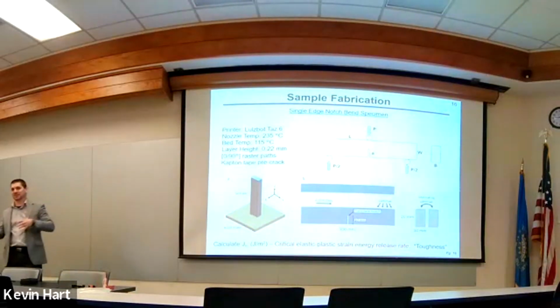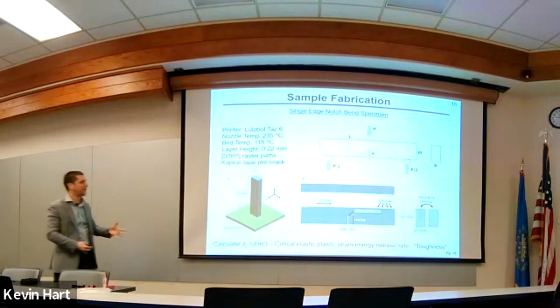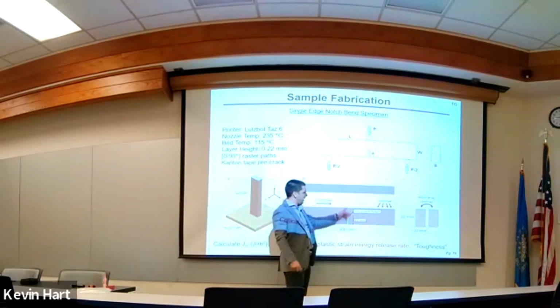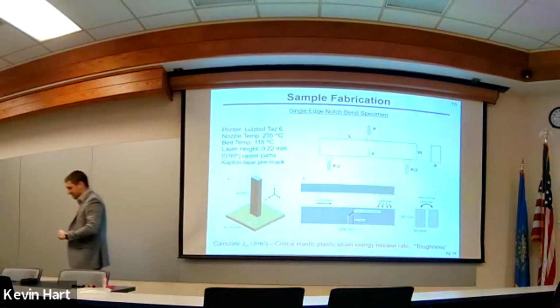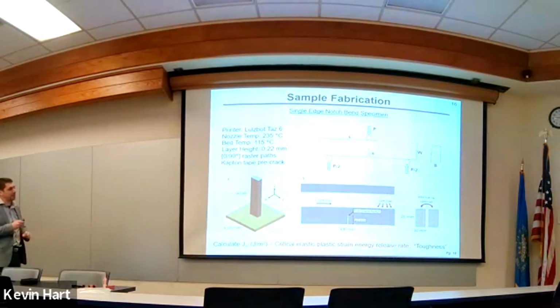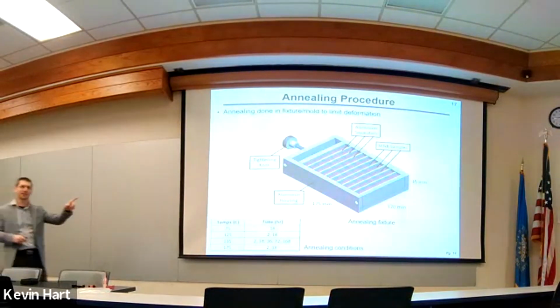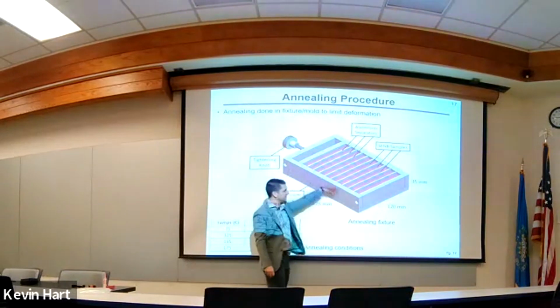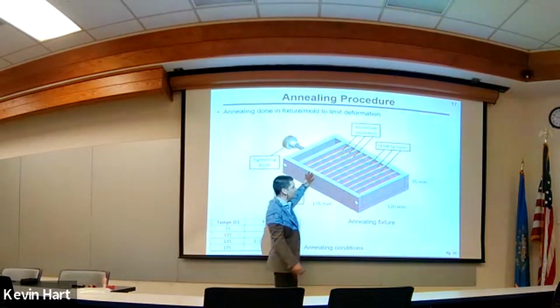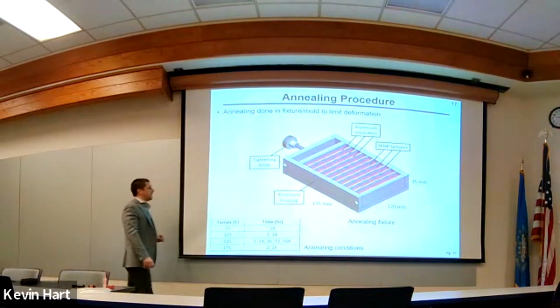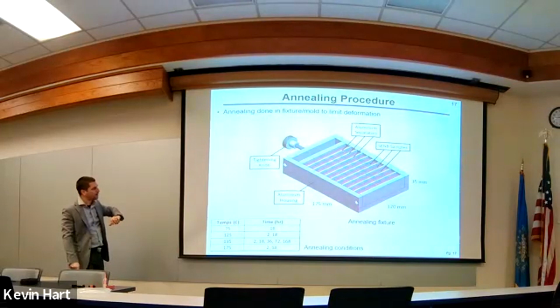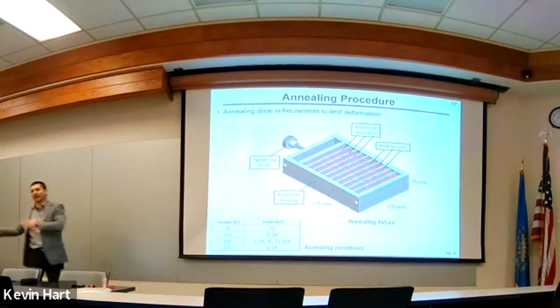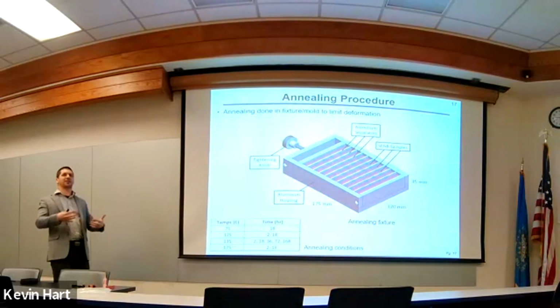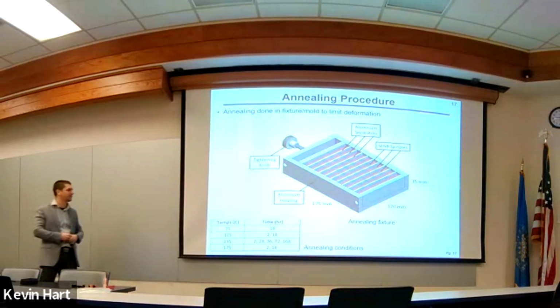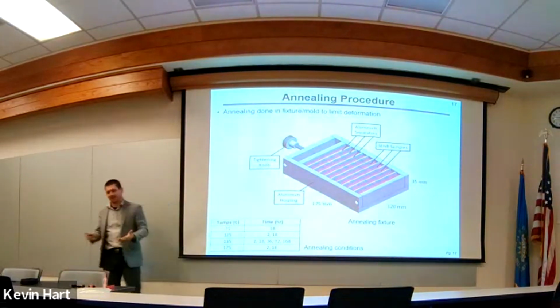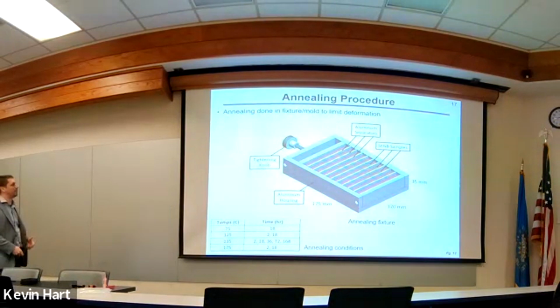So we did this. Again, we made our 3D printed samples, these rectangular prisms. We're going to do this fracture testing on them, where we put them in a frame and the crack is going to propagate upwards. We're going to measure how much energy that takes. But this time, we're going to anneal them. What I mean by that is I'm going to take these 3D printed samples and put them in a mold that looks like this. This is an aluminum mold. There are some aluminum spacers between, and we can slot in our single edge notch bend samples. They're maybe 4 inches long. We've got one going around inside the audience right now. They're about 4 inches long, maybe half an inch wide. So we can slide a bunch in there, put it in an oven, and then anneal them for certain times and temperatures and see how that affects their interlayer toughness by doing the fracture test. Generally.